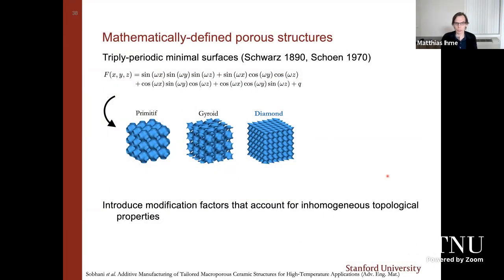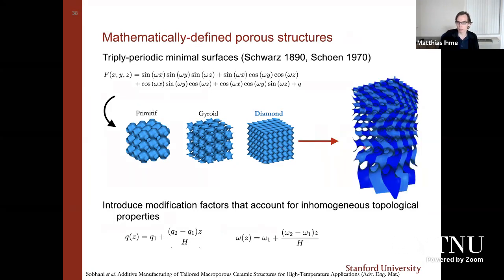So here, in order to design a ceramic structure, we're relying on a predefined topology. This is referred to as triply periodic minimal surfaces, which are essentially geometric or harmonic structures that become combined in different ways. And we have here the flexibility of changing parameters, most notably the wavelength, or this pore diameter omega, and also an offset parameter q. Depending on this, we can manufacture different structures. I just want to show you one of these designs, this diamond structure, where we're getting very homogeneous or regular pore sizes, and we are achieving a stratification in the pore diameter along the axial direction. And this is exactly what we wanted to achieve with these continuously graded porous media structures.